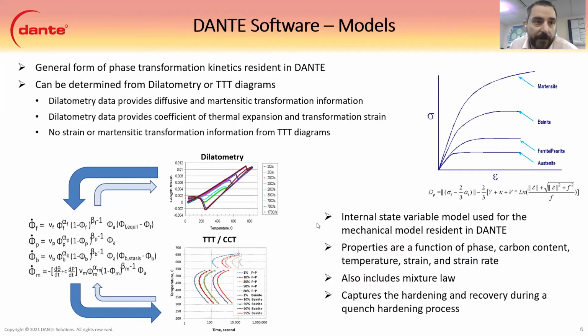So the DANTE software models, you can see this is the general form here. We fit these parameters based on dilatometry data or TTT, CCT curves. We prefer dilatometry because it does include the transformation strains that you cannot normally get with the TTT diagram, and then also the martensite start. You can't get that on the isothermal TTT diagrams. So usually that information is input when we fit from TTTs and stuff like that, and we fit to the parameters here.